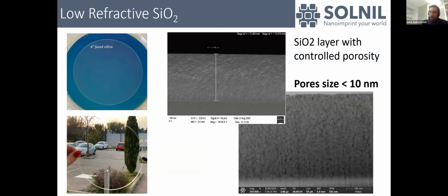For the low refractive index, the approach is quite different. We start with a silica formulation, a formulation that can, after curing, become pure glass. And what we did is that we managed to control the porosity of this layer. We managed to increase the porosity up to 75%, which allows us to reduce the refractive index down to 1.12. And to keep the optical quality and the clarity, what we need to do there is not to control the crystal size like we did for TiO2, but to control the size of the pores. So we have very small pores below 10 nanometers, and this is why we have no scattering or absorption, because the pores are very small.